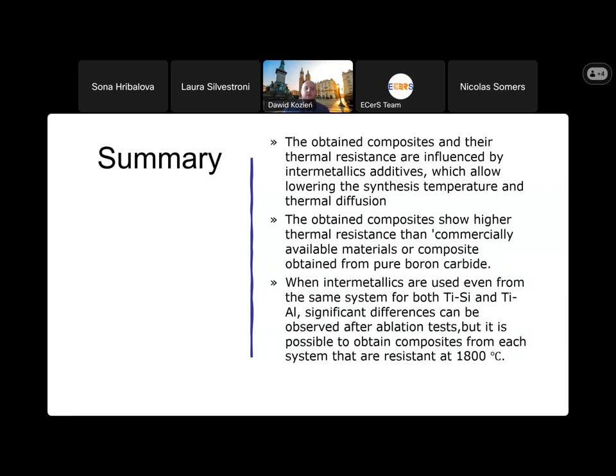But to summarize, the obtained composite and the thermal resistance are influenced by intermetallic additives, which allow lowering the synthesis temperature and the thermal diffusion. The obtained composite shows higher thermal resistance than commercially available material or composite obtained from pure boron carbide. When intermetallics are used, even from the same system, for both Ti-Si and Ti-Al, significant differences can be observed after the ablation test. But it's also possible to obtain composites from each system that are resistant at 1800 Celsius degrees. So we can obtain from each system, calculate the phases after the sintering.